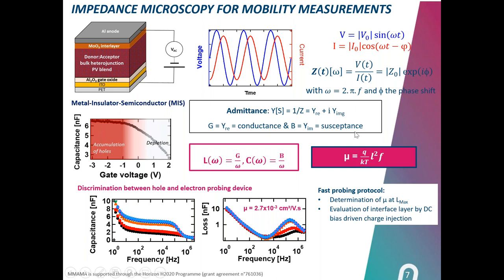So you have this simple formula in the middle. This allows for a measurement on a wide range of frequency from which the carrier mobility could be quickly obtained. The results are reproducible, the protocol is robust, some comparative tests between Keysight and Materia Nova provided the same results, and it's quite sensitive to any change, not only in the electrical properties of the active layer, but also of the interfacial layers completing the device.